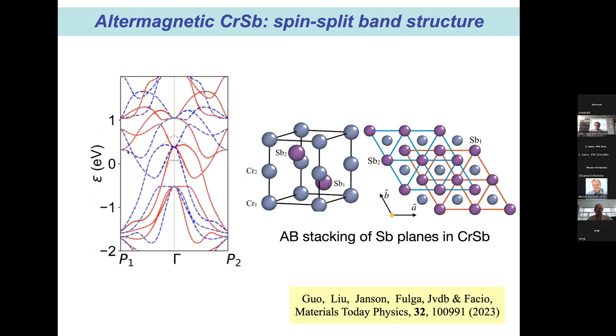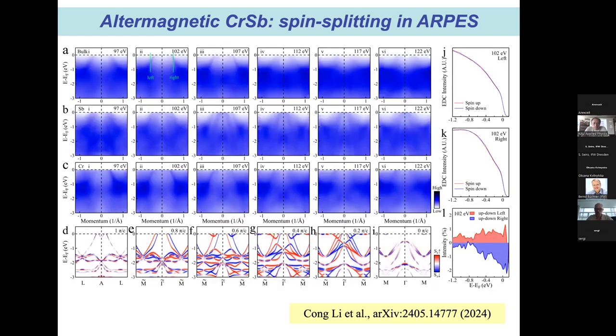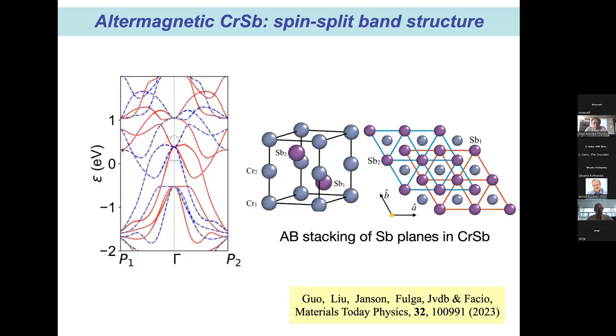And you see that in these bands, if you're at a high symmetry point, where if you do a rotation from kx to ky, for instance, you map onto yourself, then these bands are not split. So here in this case, at P1 and at gamma, the bands are not split, but in between they are split. And you see the splitting is quite large. It could be even 1 eV for chromium antimonide.